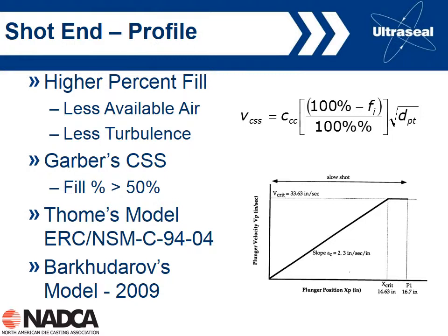And so there's been some more recent work than Garber's. For instance, Marilyn Thome at the Ohio State University came up with a better model in the 1990s. What she said is that we should use an accelerating slow shot velocity. So instead of using a constant velocity, as Garber pointed out, she said it should be an accelerating slow shot velocity. But obviously, if you're going to do that, you have to have a die casting machine with good control over plunger velocity to allow you to program an accelerating plunger velocity. But work's still going on in this area. So even as recently as 2009, a new model was proposed.